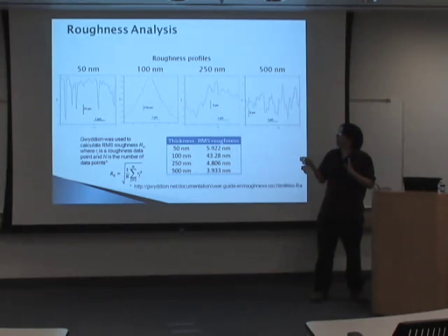These figures show how we see the surface if you're only a nanometer tall, and this gives you an excellent qualitative measurement of how rough your surface is. But we can also get a quantitative number by doing a calculation on it, and we can see the roughness ranges from 6 nanometers to 4 nanometers.